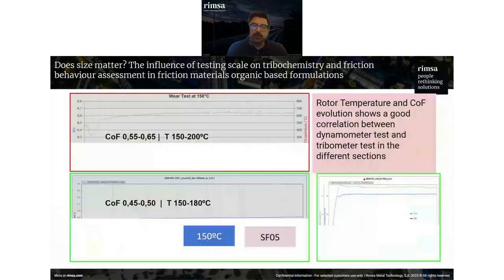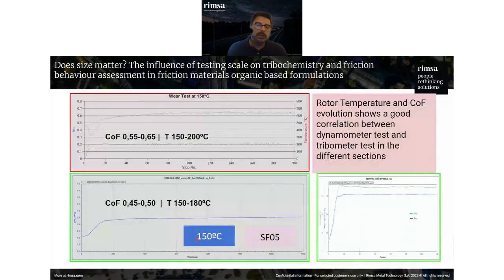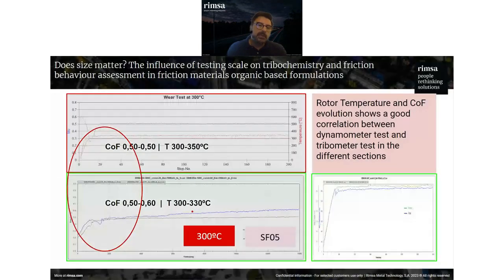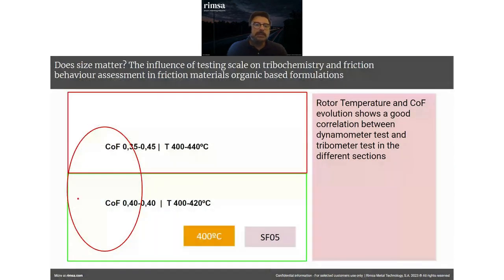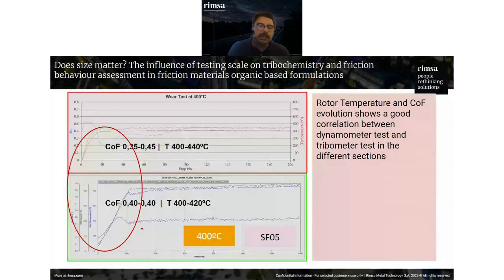If we see the results with the composite with iron and tin sulfide at 150 degrees from the dynamometer and the tribometer, we have this close profile of the evolution of the coefficient of friction. At 300 degrees, here we see a difference, but still we have this small drop. Here the drop is bigger, but then the coefficient of friction is pretty close. And at 400 degrees, we have a slight difference here in this initial area.